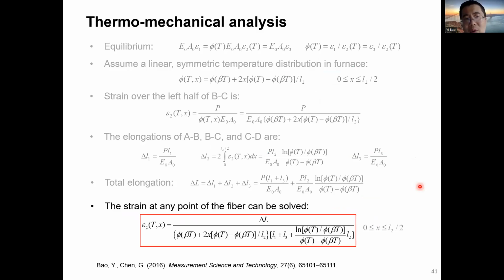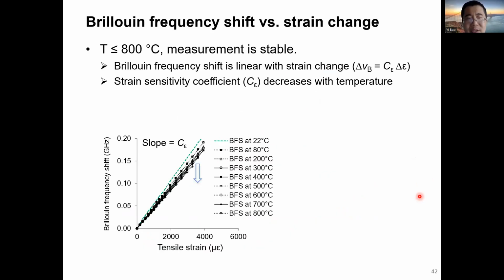So to solve this problem, we conducted the thermomechanical analysis. I'm not going to elaborate the mathematical work here, but eventually we were able to relate the strain value to the length change of the sensor. Therefore, we can improve the calibration accuracy. After we calibrate the sensitivity of the sensors at the elevated temperature, we apply the sensors to measure both temperature and strain. And a very interesting phenomenon we observed was that the sensitivity coefficients, like strain coefficients, were dependent on temperature, which means the linear equation I showed you at the very beginning of this talk will not be valid anymore when the temperature is high. But based on our calibration work, based on the thermomechanical analysis, we were still able to calibrate the strain and temperature sensitivity coefficients.